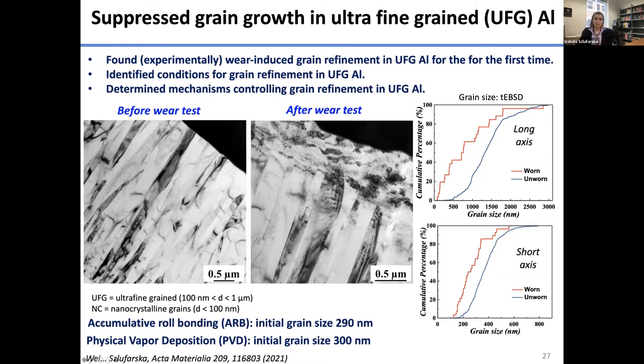And so this is basically the punchline of the story. Here's a TEM image of the sample before and the sample after, and you can see that near the surface, there's a tribological layer with these nanocrystalline grains. So that's quite exciting.